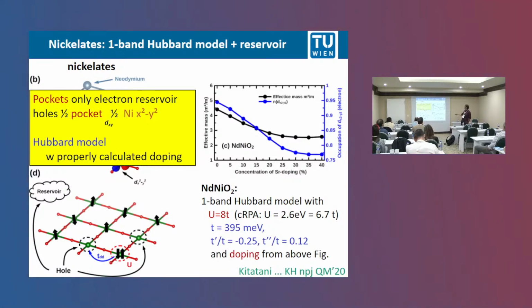And you see even at 0% strontium doping, you have already about 5% holes in your x squared minus y squared orbital. That is because you have electron pockets, so some of the electrons are moved away from the x squared minus y squared orbital and are instead in these pockets. And that also nicely explains why there is no long-range antiferromagnetism in the nickelates, in contrast to the cuprates, where for the parent compound you always have antiferromagnetic long-range order. If you have a 5% hole-doped cuprate, you wouldn't expect long-range antiferromagnetism either.